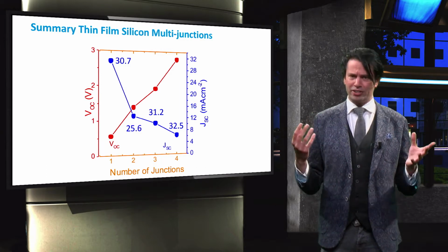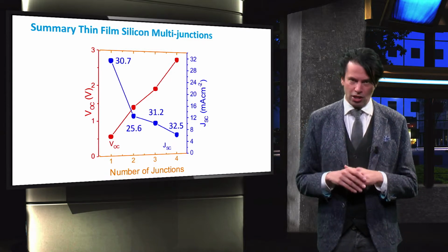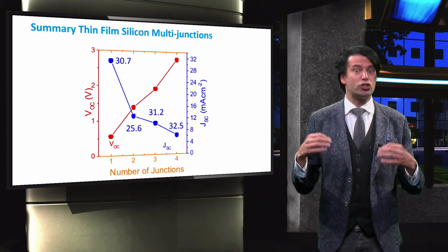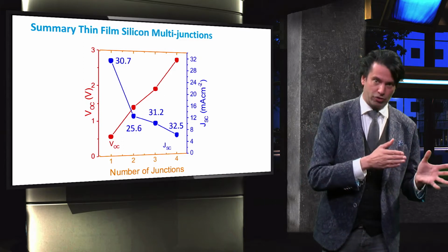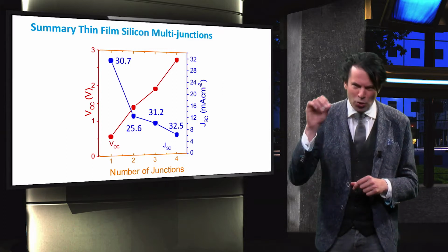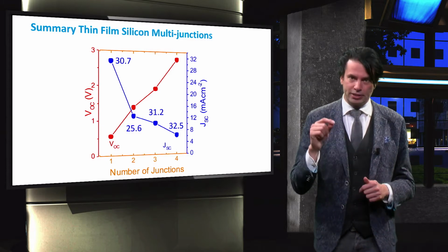This shows that the record tandem and quadruple junction PV cell is either far from the current matching, or the cell architecture still suffers from parasitic absorption losses. Note that both single and triple junctions are solar cells in the substrate configuration, and the tandem cell and quadruple cell are in the superstrate configuration. This suggests that at least the parasitic absorption losses in the superstrate cell configurations play a more dominant role in quenching of the photon utilization. The main reason is the front electrodes based on TCO.